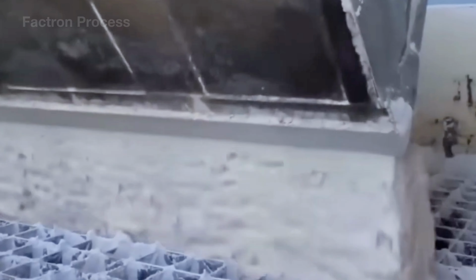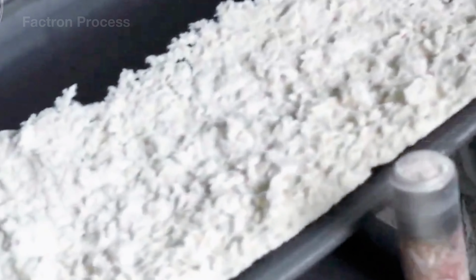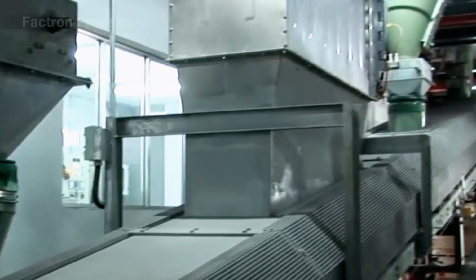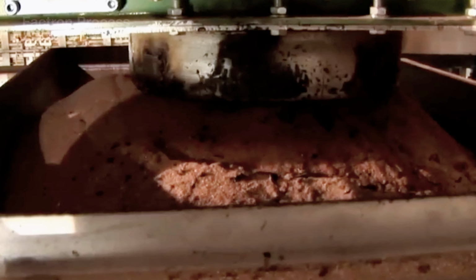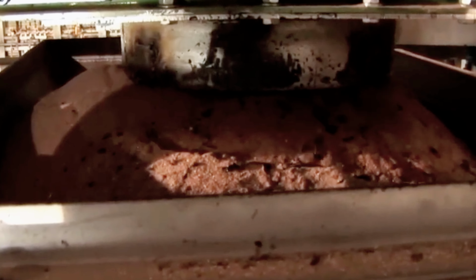Clean cullet is weighed and mixed with silica sand, soda ash, and limestone. The amount of cullet depends on the glass color, material cleanliness, and final product requirements. Because cullet melts more easily than raw minerals, using more of it helps save energy. The mixture is then fed into the furnace and transformed into molten glass.